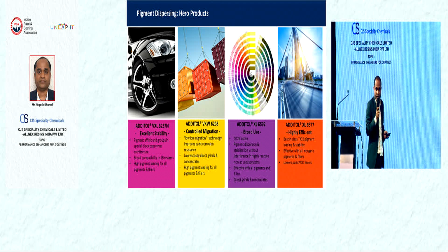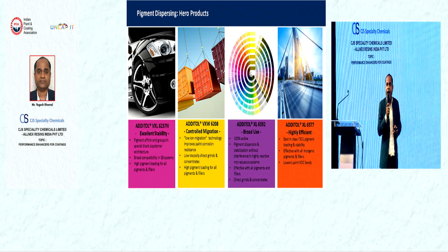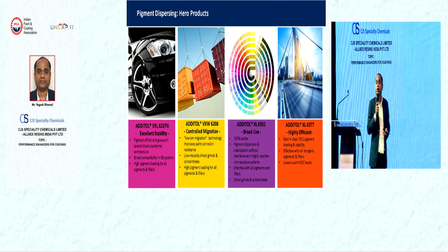Very unique chemistry, I would say here. It is controlled migration. Why controlled migration? This particular additive wets or disperses the pigments in such a way that it coats the separated pigment particles, and it doesn't allow the ions on the pigment particles to migrate and lead to corrosion of the metal substrate. So that's why it acts as a low ion migration technology, and it helps to improve the corrosion resistance of